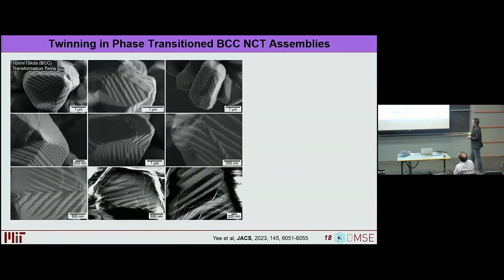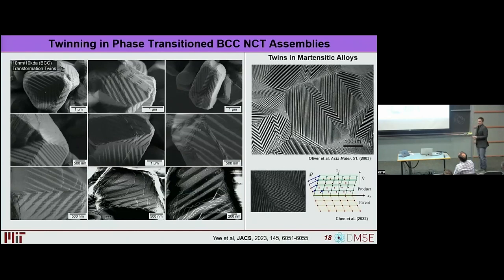If we look at these types of structures, they are recreated across virtually all of the assemblies that we see. And what we think this is basically a martensitic phase transition. So if you talk to a metallurgist, this is a common thing. If you've got austenite going to martensite, you're going from an FCC to a BCC type structure. And essentially the way it does it is it basically slips along certain planes in order to alleviate that strain. So what we think is going on is as we're compressing our lattice, it gets to a point where the particles just can't take it anymore, and they basically shear, going from an FCC to a BCC type case in order to alleviate that strain.